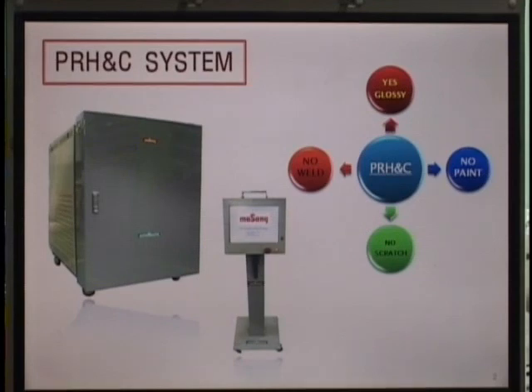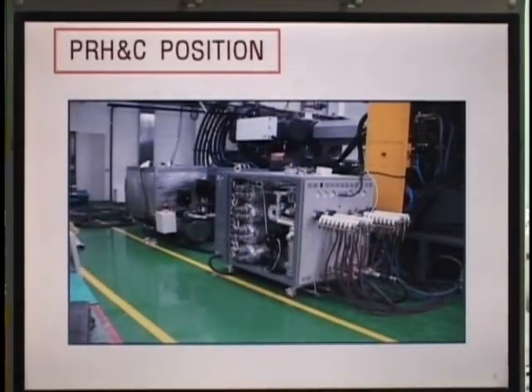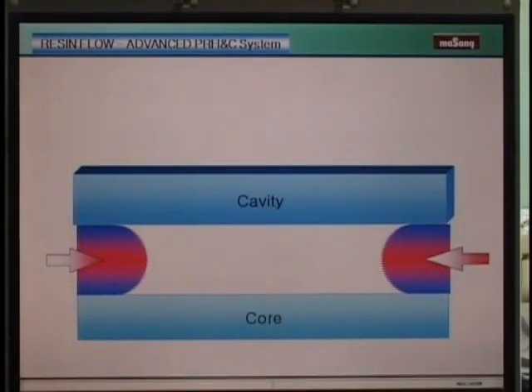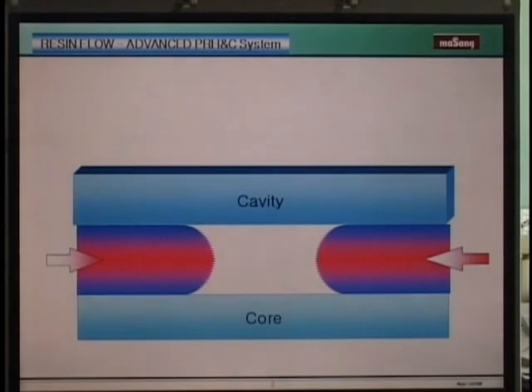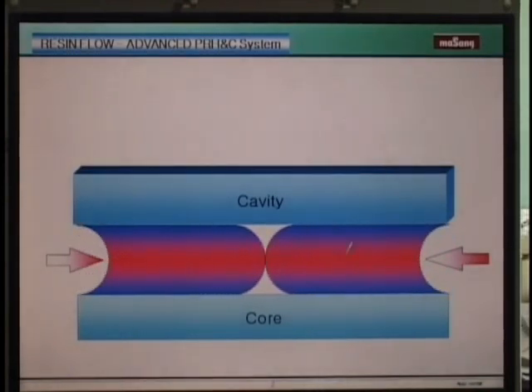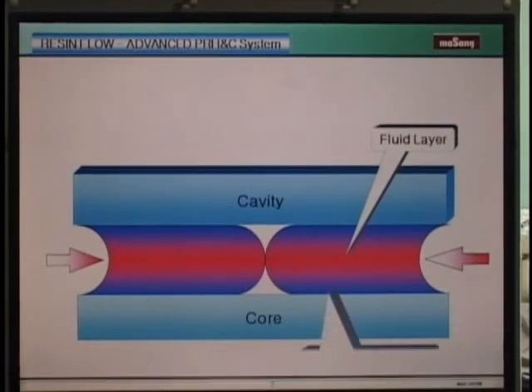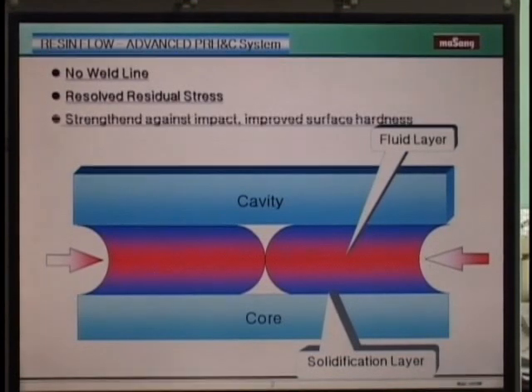In the high pressure state, the water temperature goes up to 180 degrees at max, and this consists of the body, touch screen, and heat exchanger preventing scale. As seen on the screen, a weld line is formed at the junction of two resins, because resin is solidified as the mold temperature is low. In the low temperature, the weld line is clear. To the contrary, as the mold temperature is higher, the weld line becomes weaker.